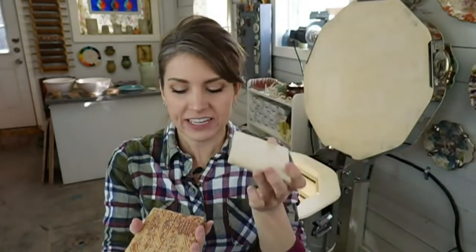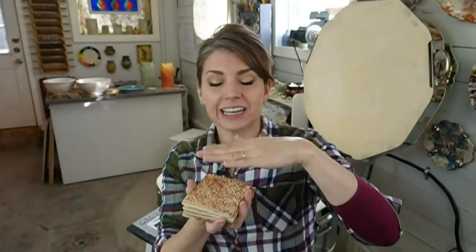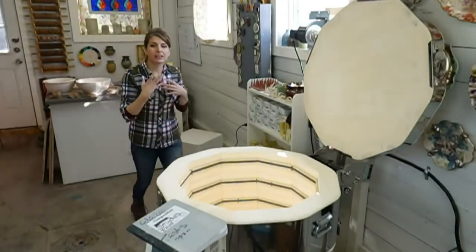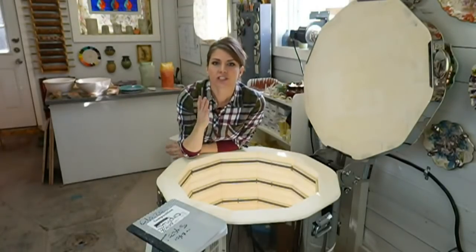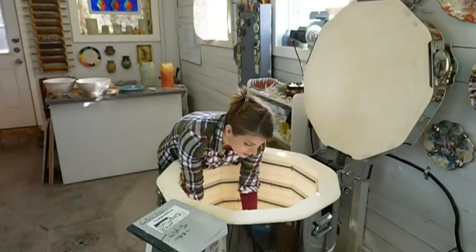How do I keep my tiles from warping? Sharon, I'm actually going to do that on this week's live broadcast, making tiles. And we can talk more about that then. But what you do is you make your tile, and then you lay it down on a board, upside down, meaning the pattern face down, and then you put another board on top, and you weigh it down with something. Usually I'll stack more boards on it because I'm making a lot of tiles, but you need to press them flat and keep them flat until they're 100% dry, and then when you fire them, make sure your kiln shelves are nice and flat. Because if you have a warped kiln shelf, that will warp your tiles. And you might not realize over time, your kiln shelves can do this thing called cupping, where they just start to bow a bit. So you can always check your kiln shelves to see if they're doing that. If you're noticing a lot of warping on your pieces, that could be the reason why.